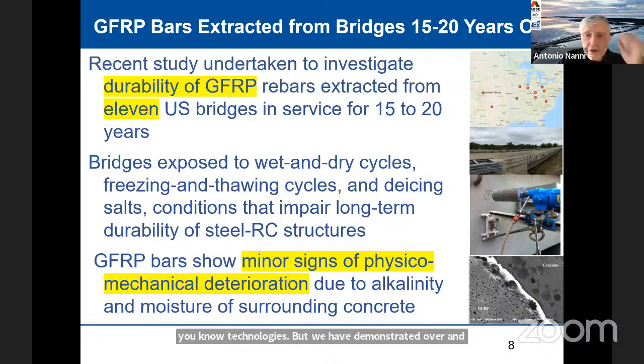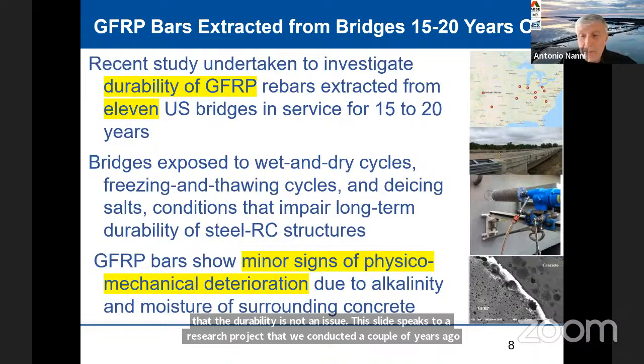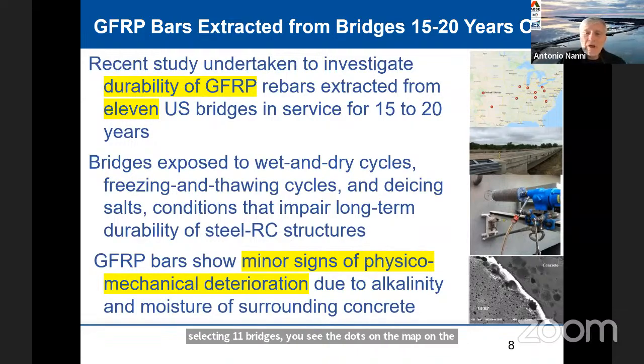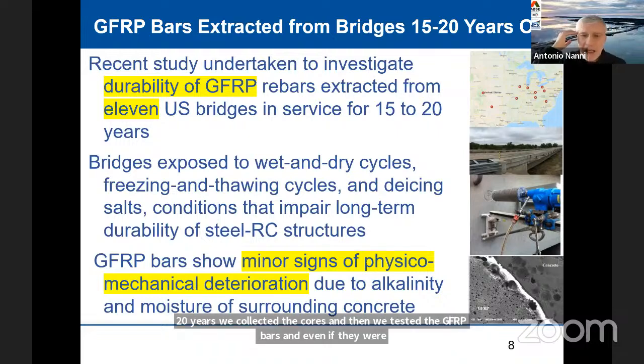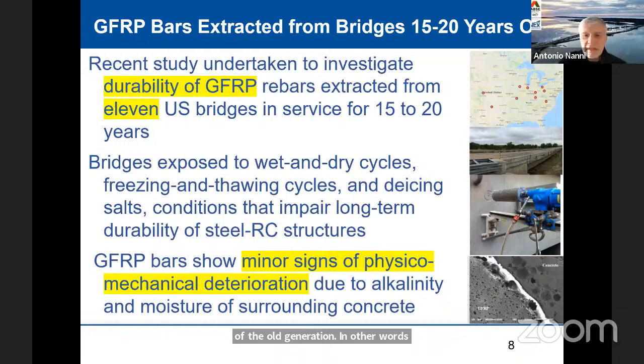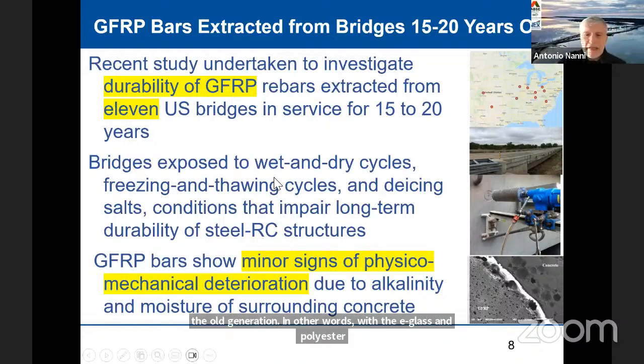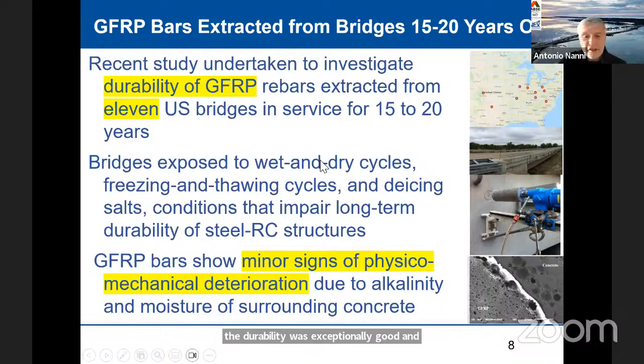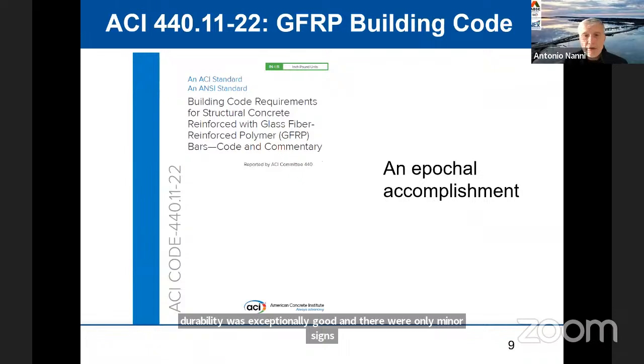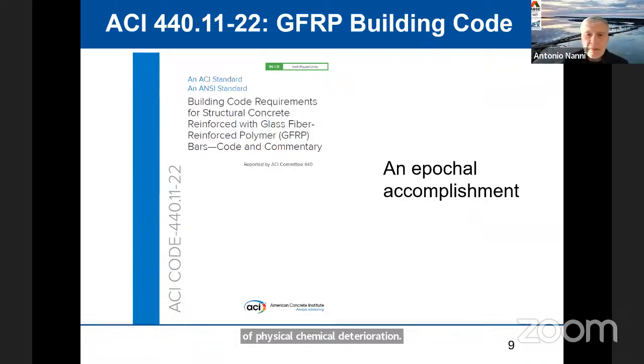This slide speaks to a research project that we conducted a couple of years ago, selecting 11 bridges. You see the dots on the map on the right-hand side that were built over a period of 15 to 20 years. We collected the cores, and then we tested the GFRP bars, and even if they were of the old generation, in other words, with E-glass and polyester, the durability was exceptionally good, and there were only minor signs of physical-chemical deterioration. So now let me switch gear very quickly to the building code.